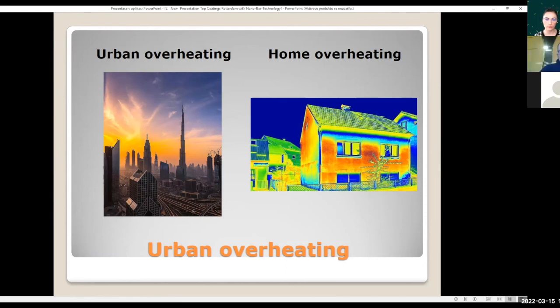Also this is the situation when there was direct shining. The red and dark red color means it is very, very overheated, and it has influence on the building. If the glasses in the windows are not coated, it will push the temperature inside the building much more. This is one of the ways. As I told before, we cannot eliminate 100%, but I think 15 degrees is relatively good.